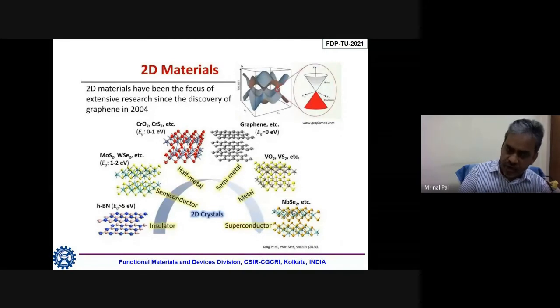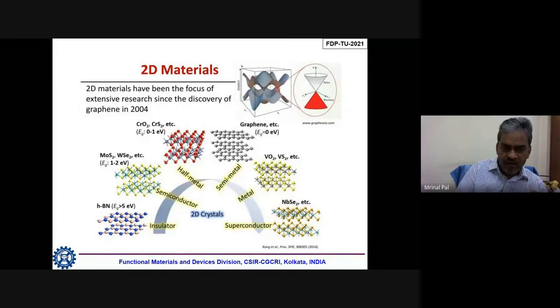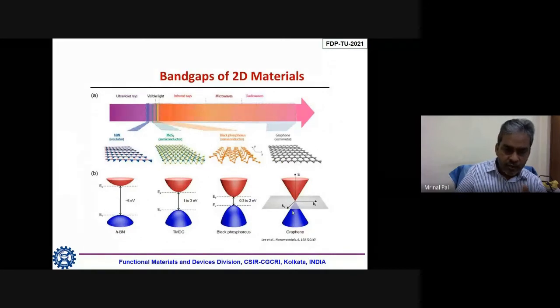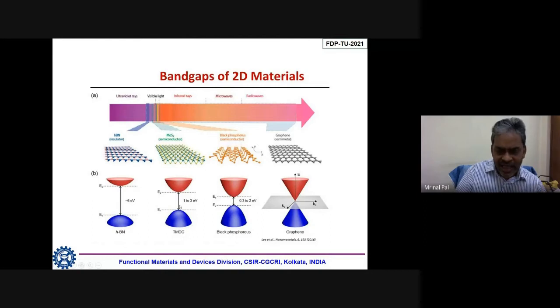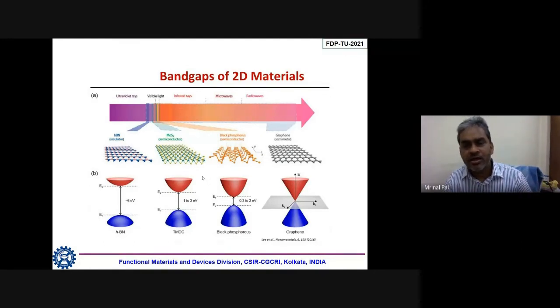People are working on different kinds of 2D material, which I have mentioned, starting from graphene to hexagonal boron nitride to molybdenum sulfide to new superconducting materials like niobium selenide. And if you look at their band gap, on the left-hand side, this is the band gap of hexagonal boron nitride, which is more than 6 eV, which is truly an insulator. These are transition metal chalcogenides, like molybdenum sulfide. They have a band gap of 1 to 3 eV. They are semiconducting. Also, this is black phosphorus, which has a very small band gap, between 0.something to 1 or 2 eV. They are semiconductors or semi-metals.